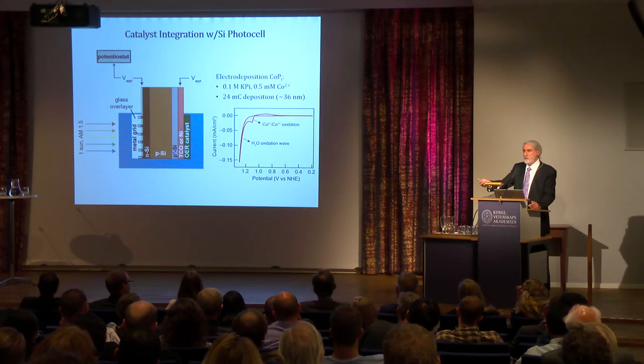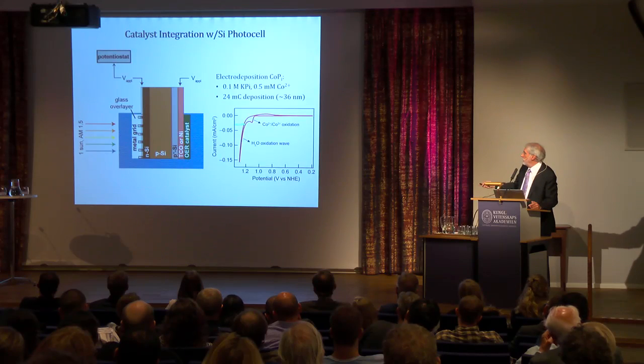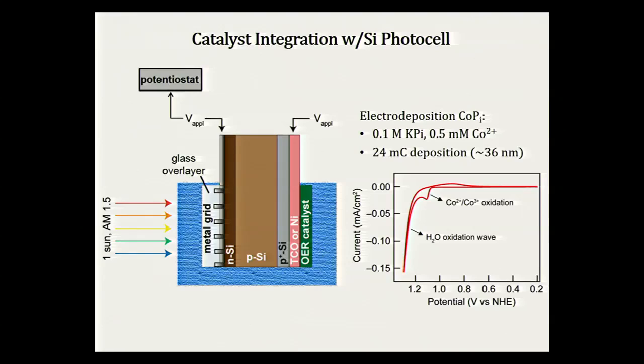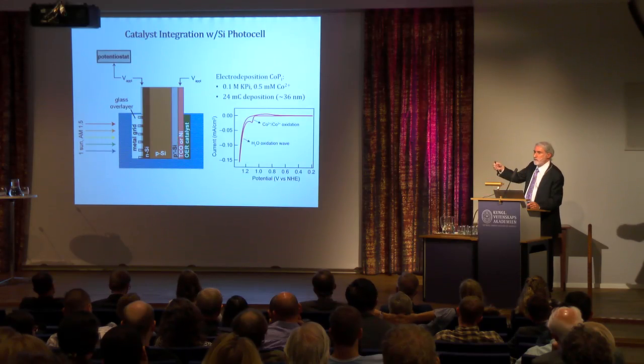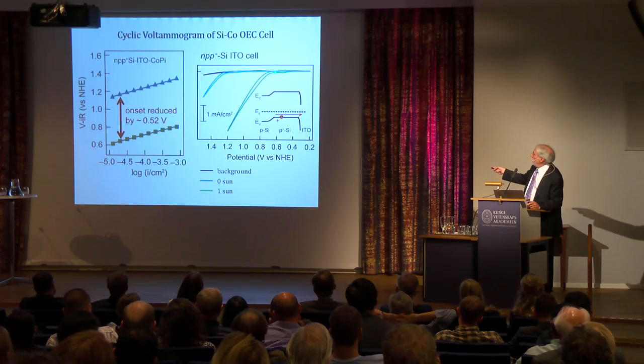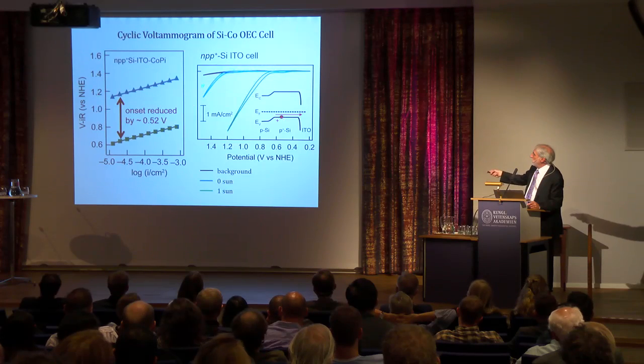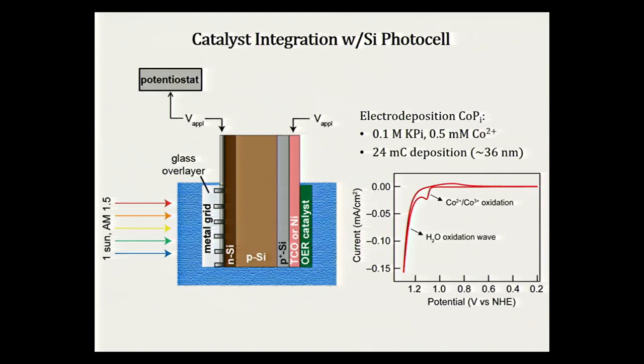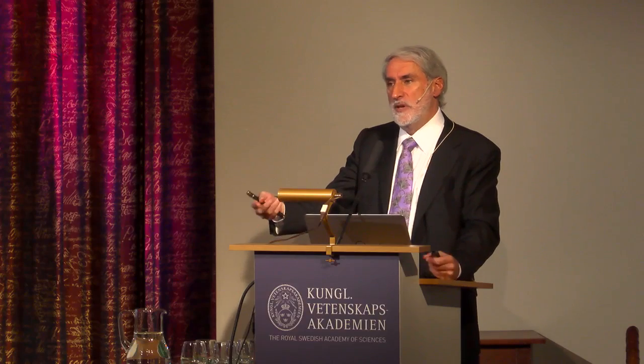When we oxidize cobalt-2 to 3, you make the catalyst coating. And so here, this is the self-assembly process, and then this big wave here is where you're making oxygen. You're passing lots of current, because all the current's going into oxygen. And so this looks like an electrode. This is what you would do in electrochemistry. Now, here's the curve I just showed you in the dark. The special thing about this electrode is I have silicon. So when I put sunlight on it, I internally generate 0.57 volts. And I separate an electron and hole through a potential of 0.57 volts.